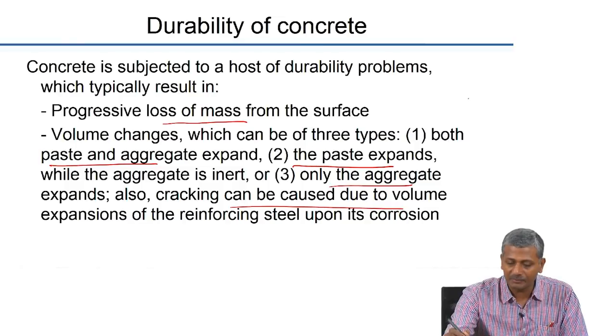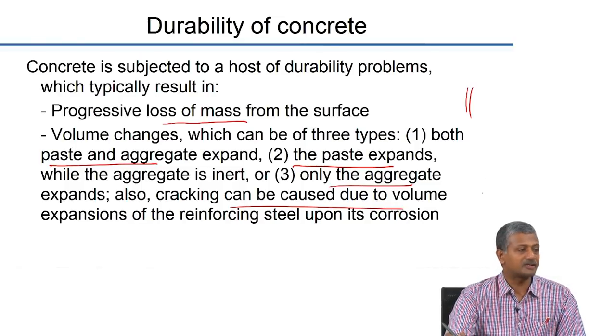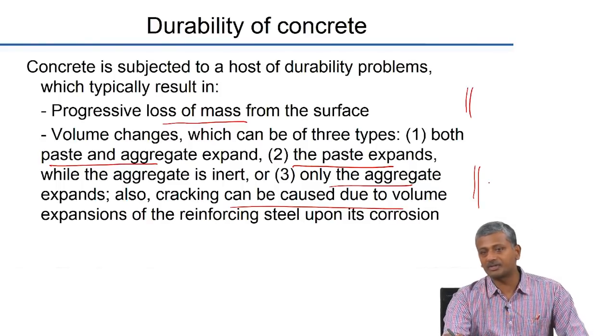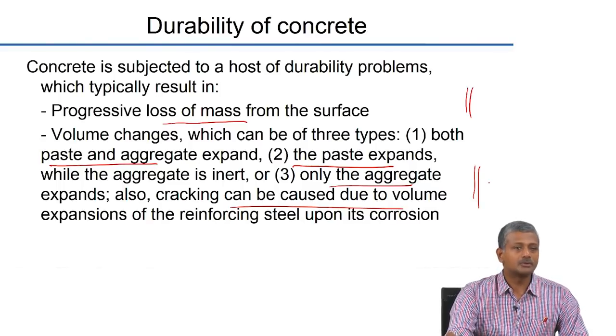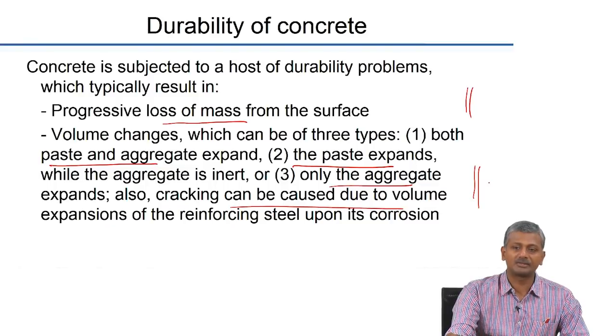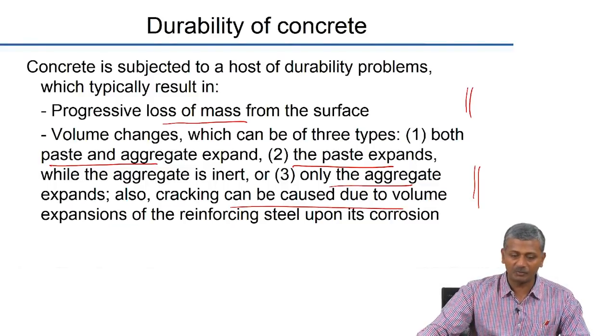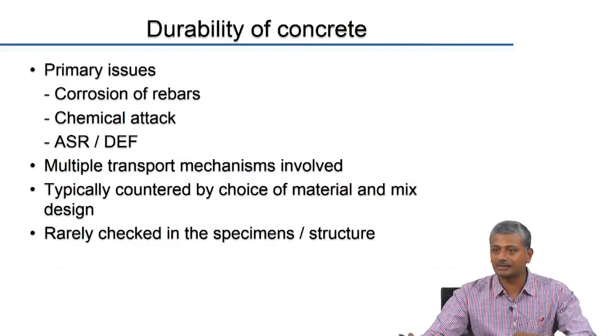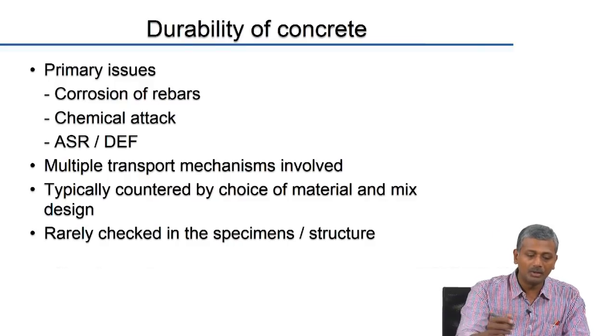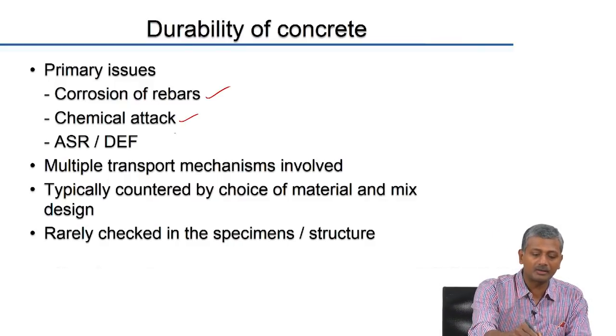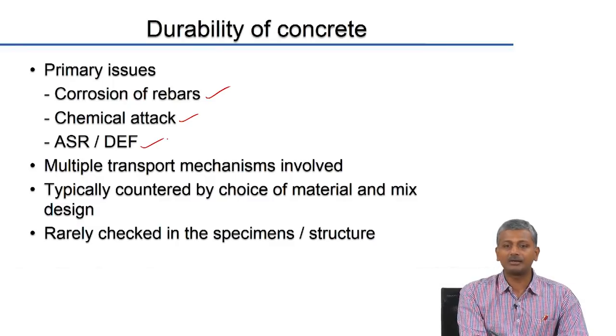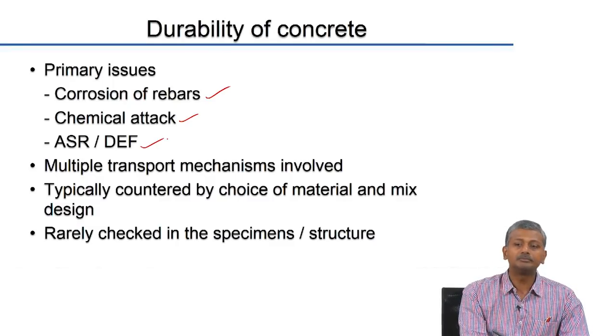So you have two different types of manifestations. One is loss of mass from the surface, the other is expansion of the concrete, which is caused by several different scenarios, right? So this is a common thread between these issues, and one more common thread exists between durability problems. Of course, these are the different durability problems that we are talking about: corrosion of rebars, chemical attack, alkali silica reaction, delayed ettringite formation. These are the primary issues that we deal with as far as durability is concerned.